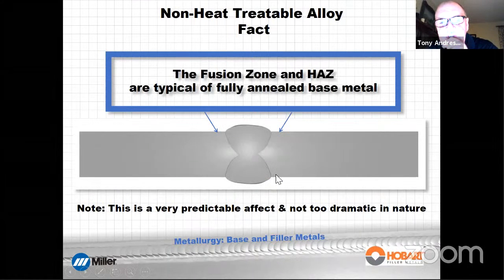All right. So what actually happens when we weld this material in that strain hardened condition? Well, the temperature of the weld in the heat affected zone is such that it will return the material to its annealed strength, right? It will no longer have that high strength. The rest of the material is unaffected, but the heat affected zone will return to the annealed condition. That is unavoidable, cannot be helped. The good thing is that it's predictable. We know exactly what it's going to be, so we can design around that strength.